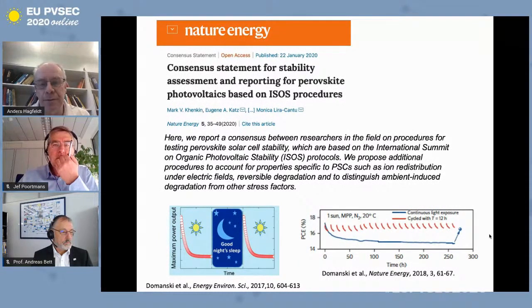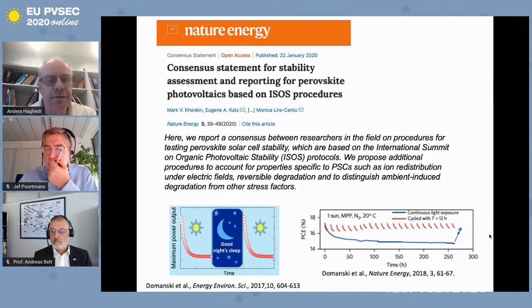For example, we know that one issue with the measurement of stability is that there is a dynamic behavior where we can see that initially the efficiency goes down, reaches a constant value, and then if we switch off or we have night, let's say, without sunlight, the efficiency goes back again. So it's a reversible decline which goes back up, back and forth, and we in the paper discuss how to take that into account when we do measurements, either if we follow continuously over time or if we chop the light in cycles, let's say, as you see here.